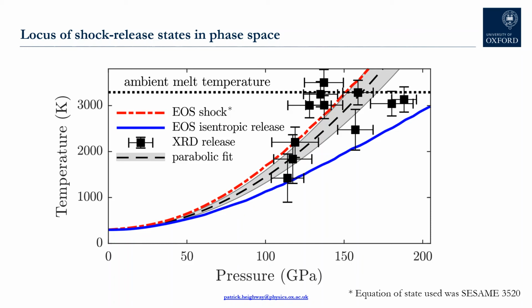We see that, in agreement with the simulations, the temperature of the crystals following release always exceeds by some margin the isentropic release temperature at that shock pressure. Interestingly, the temperature of the crystals does not actually increase without limit, but saturates at the ambient melt temperature at shock pressures of around 150 GPa.